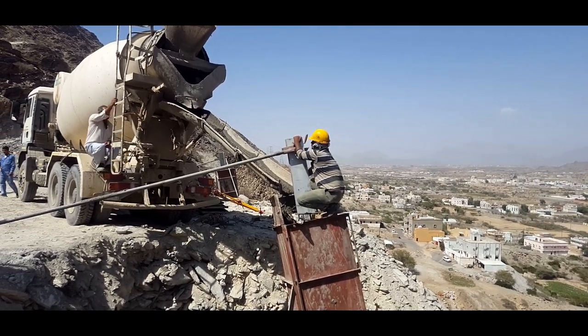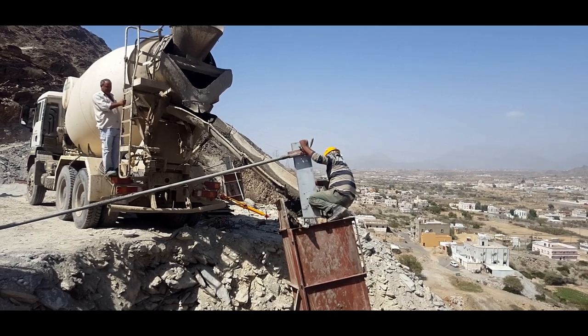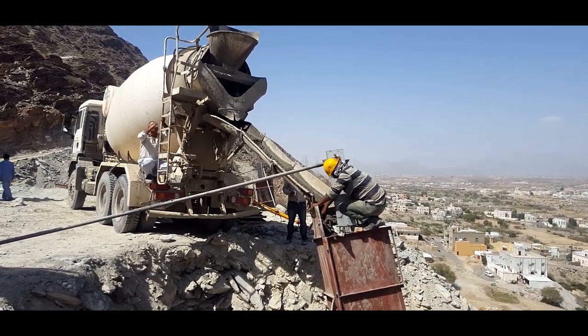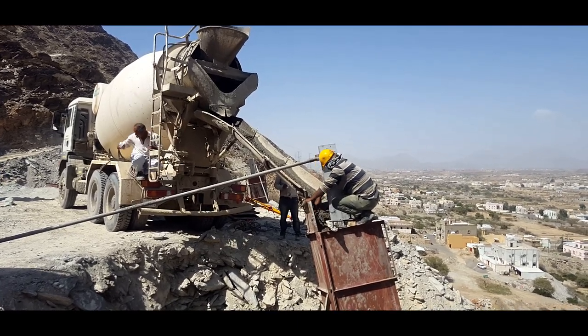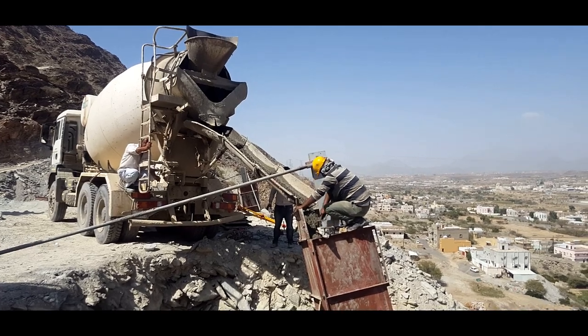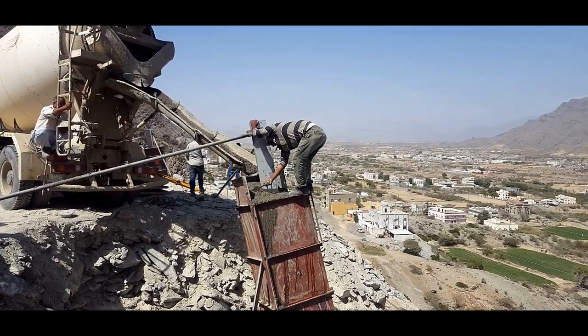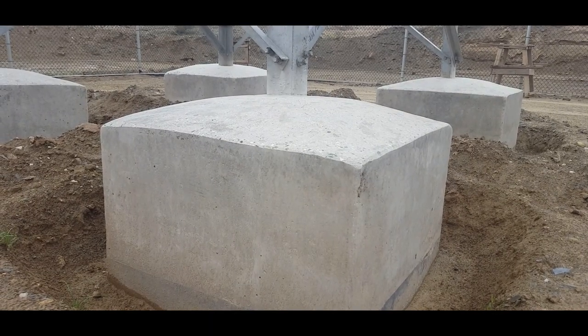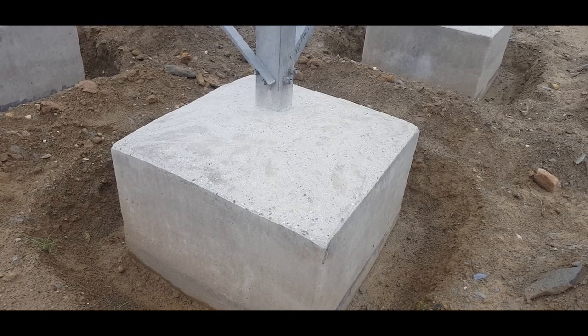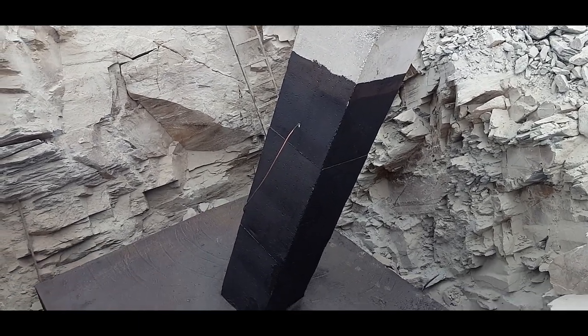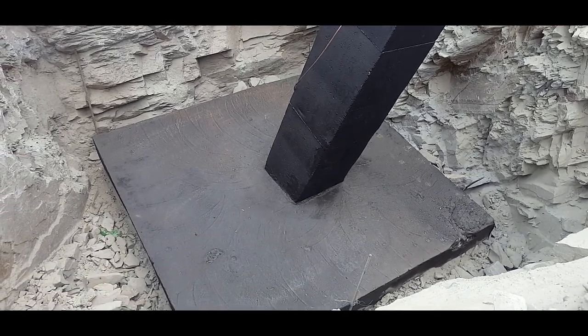A curing period of minimum 10 days is required after the concreting is completed. This enhances the strength and durability of concrete. The top of the foundation is coped at an angle of 15 degrees starting from the heel of the stub, to prevent accumulation of water below grade surfaces. The primary use of tar coat is to protect the concrete surface from chemical attack and ingress of water and gases.